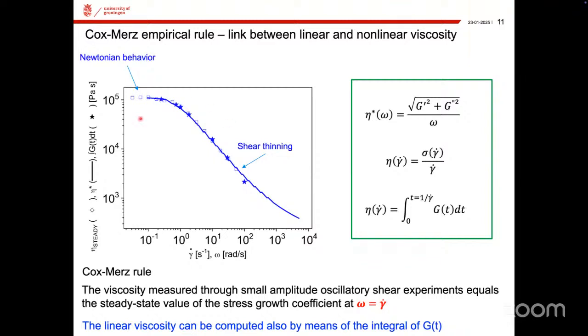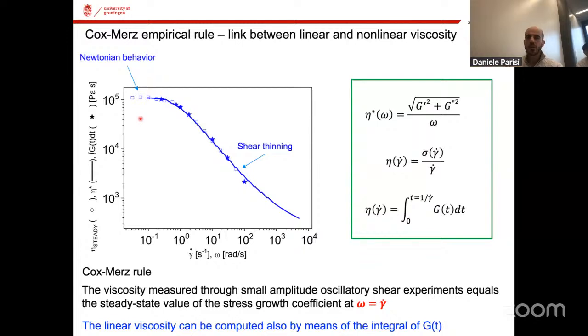So in this plot here, we have not only the viscosity that we get from linear viscoelasticity, which is basically connected to G prime and G double prime, and we call this complex viscosity. But we can also use the rheometer in steady shear deformation, where we can get the so-called steady shear viscosity. So there is a third way to get the viscosity, but okay, it's not really relevant over here. So with this, after this very brief introduction, let me show you the juice and the core of this presentation.